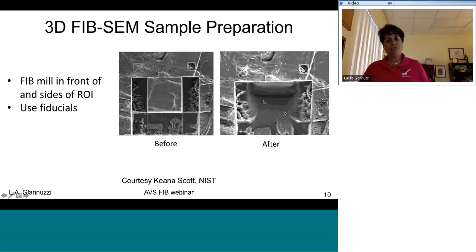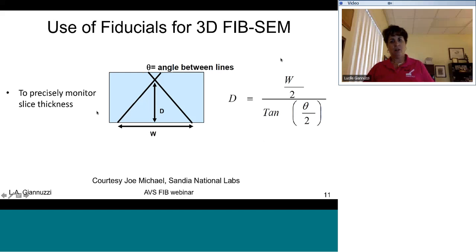Okay? It's also necessary to use fiducials so that when you FIB mill each area, the beam knows where to go to the next slice. And there's also fiducials that you can use for SEM imaging so that it goes back to the same slice as well. So it's also often useful to use fiducials on the top of your sample surface. This is so you can precisely monitor the slice thickness. So from the top here, you can make 2 lines where theta is the angle between the lines. And then D here, you can get an accurate measure of the slice thickness by how D changes as a function of time.